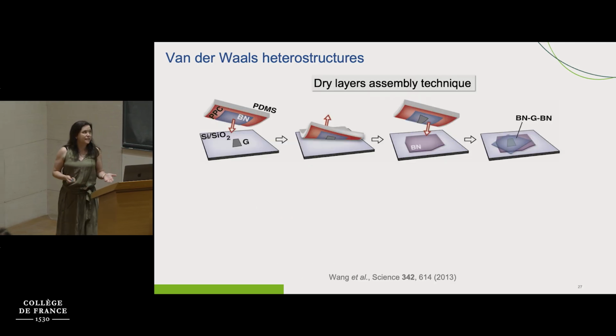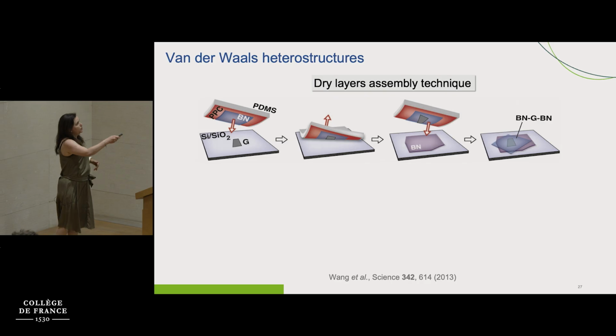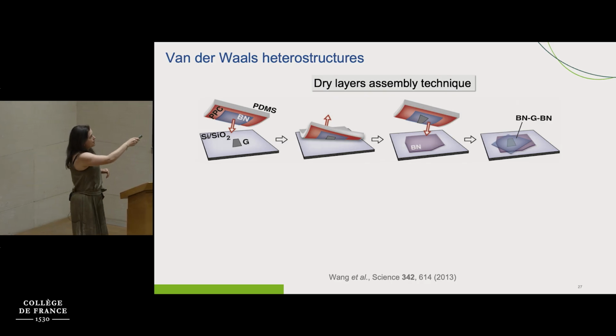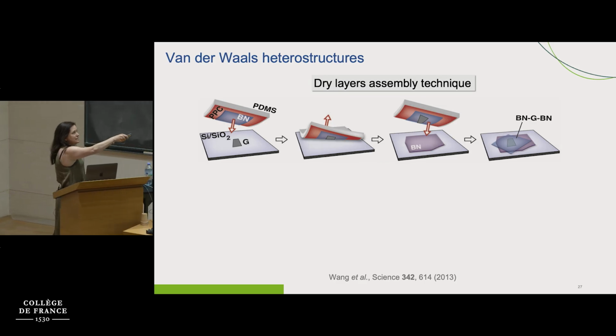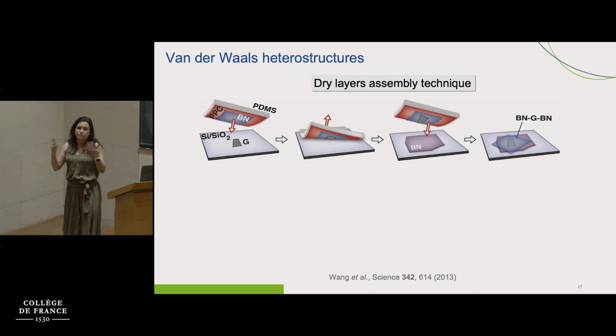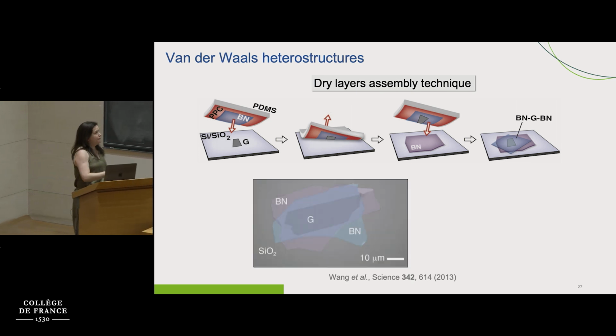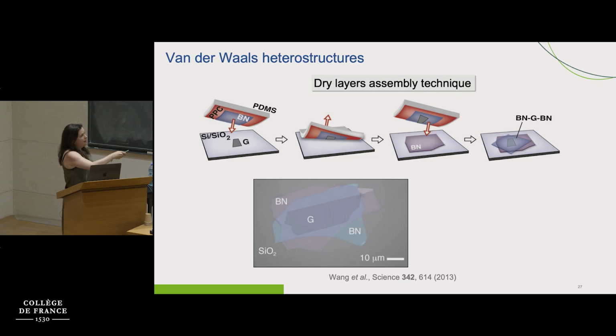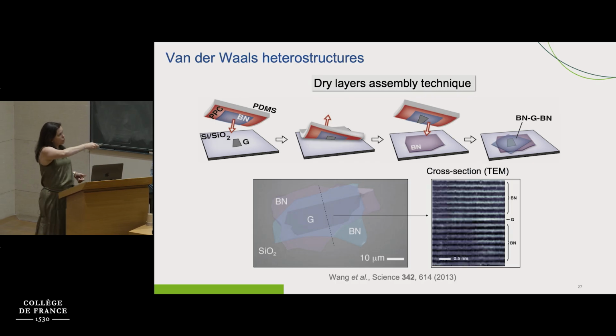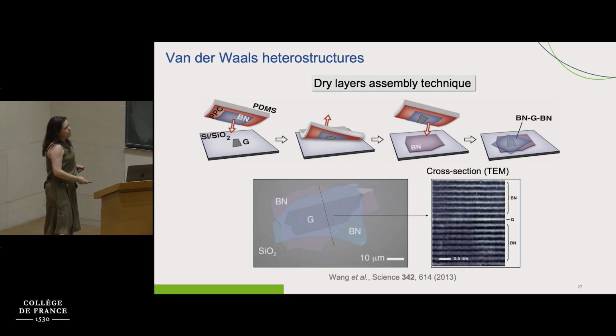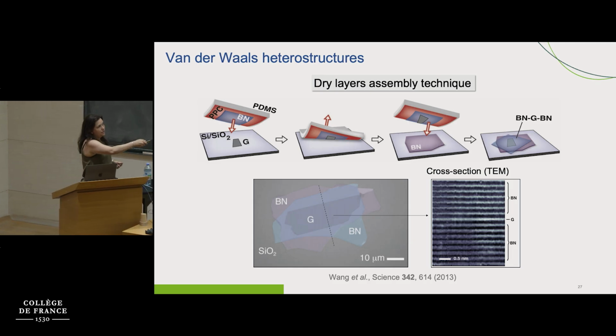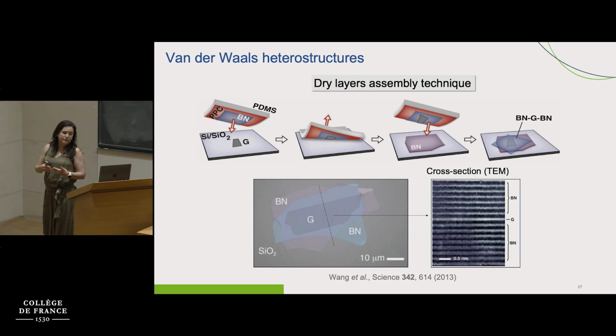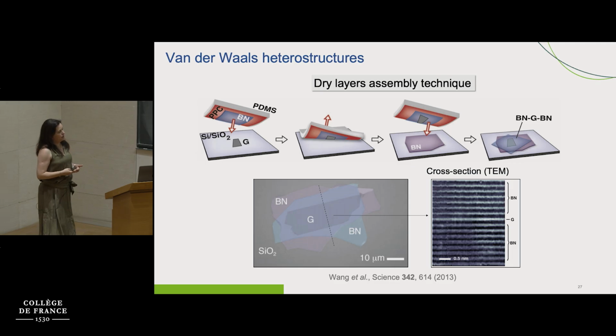The way we do this, I think Dima already explained, but I'm just going to pass through it quickly, is we take a polymer, we pick up the first layer, with this one we pick up the second one, the third one, etc. So this guarantees that the graphene that we have in the middle is always clean. It's going to be perfectly clean. And in fact, if you take one of these stacks of 2D materials and you make a cross section, you can see in TEM measurements that there is nothing between the layers. There are only van der Waals forces holding them together.